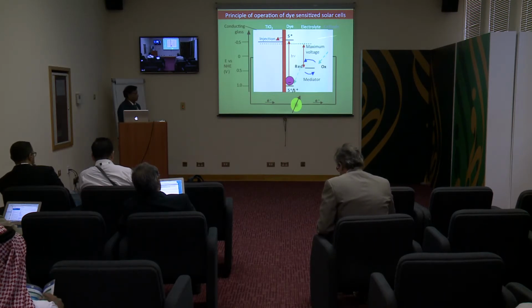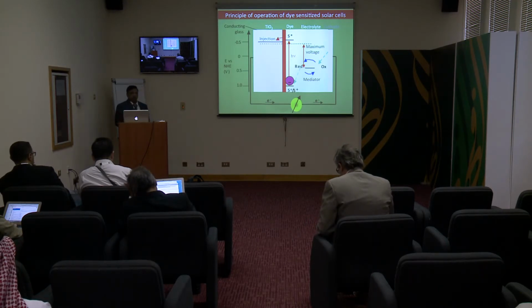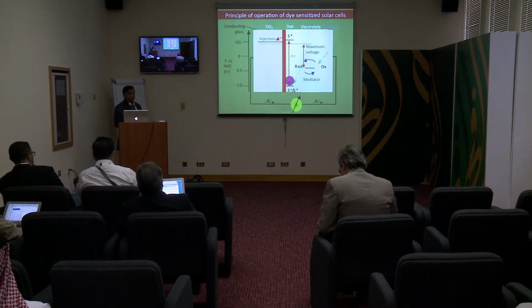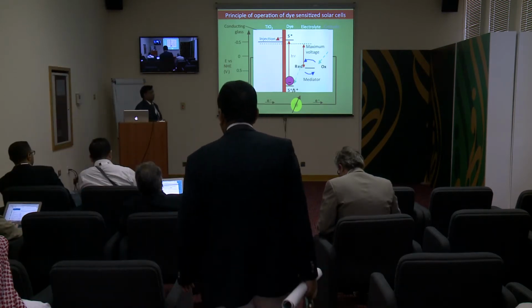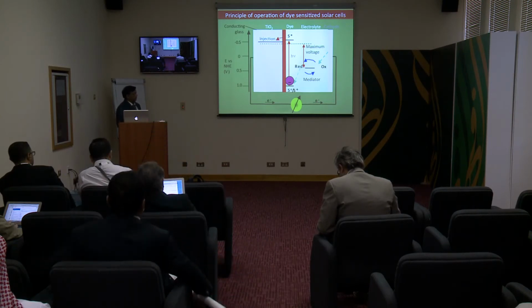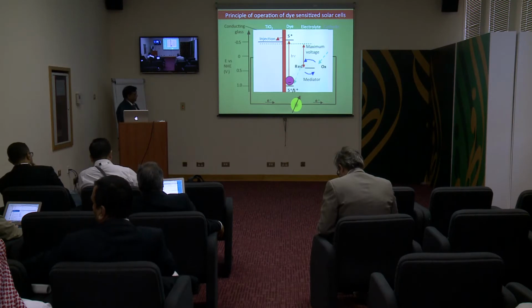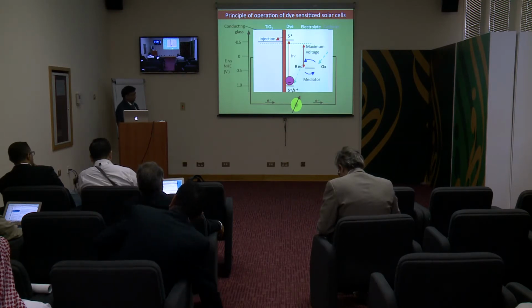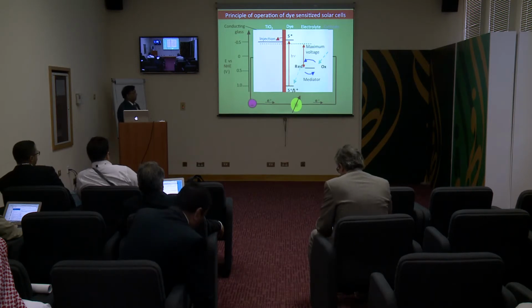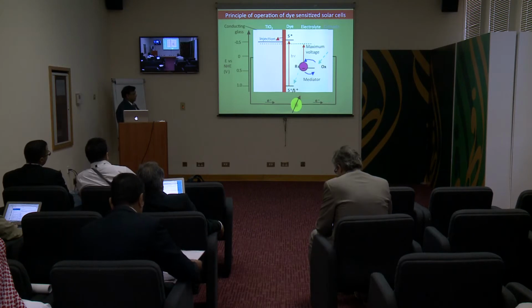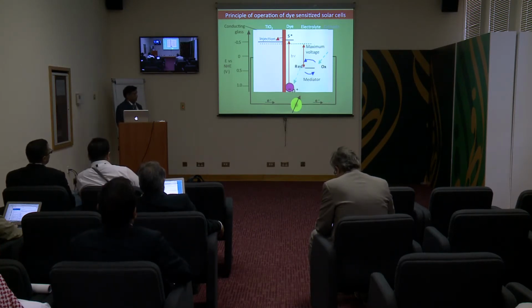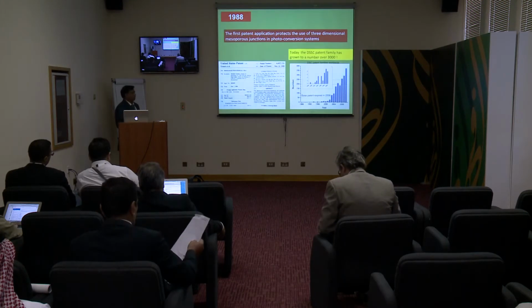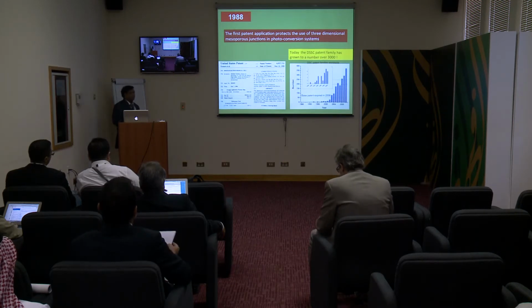Basically, we use two transparent conducting oxide substrates. One has TiO2 deposited as a photoanode, and the second conducting glass is used as a counter electrode, where we use platinum as a catalyst to reduce the triiodide. Once light is absorbed on the photoanode, the dye goes to the excited state and injects electrons into the TiO2. The injected electrons percolate through the film and go to the back contact, and the oxidized form of the dye is regenerated by the electrolyte, which diffuses to the counter electrode to be re-reduced. This is the operating principle of how the dye-sensitized solar cell works.